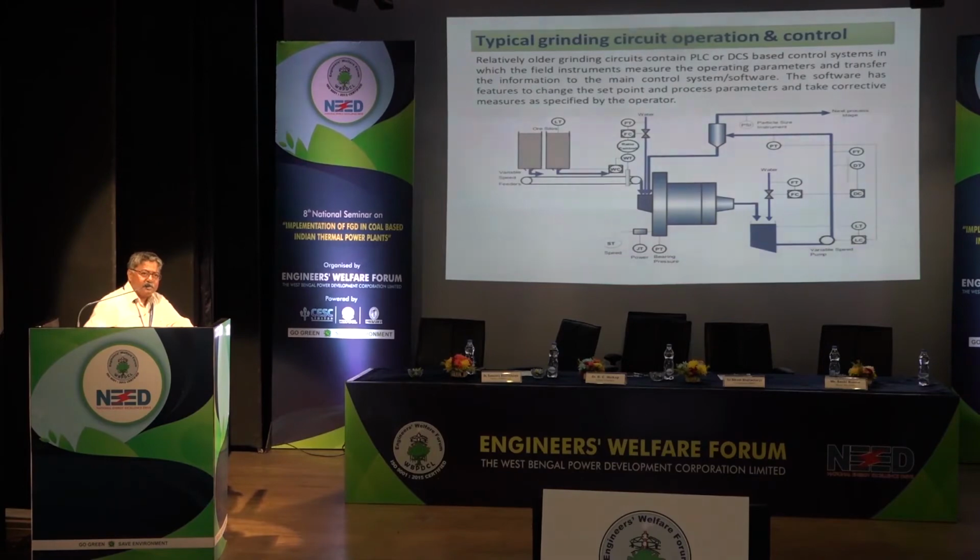Why? Because larger the concentration, more is the coating of particles on the surface of the balls. More is the coating on the liners inside the mill. More coating, more grinding. Less coating, much more wear and tear, because more and more iron to iron, cast iron to cast iron contact. So reduced life of mill, reduced life of all its parts, reduced life of balls, faster de-shaping of the balls. So very important is pulp density control through feed rate control and water flow control. Both are required.